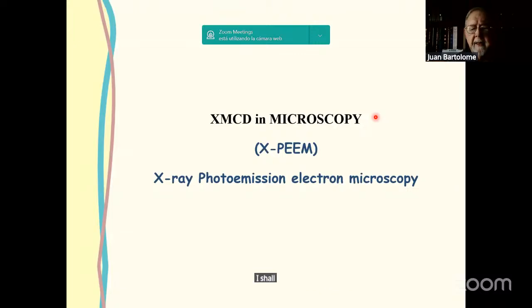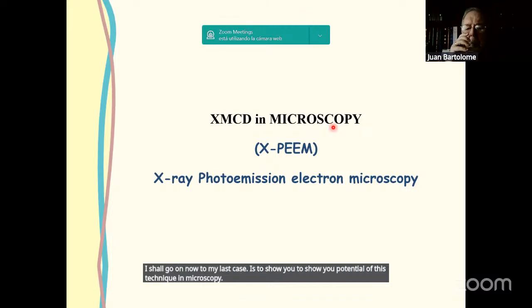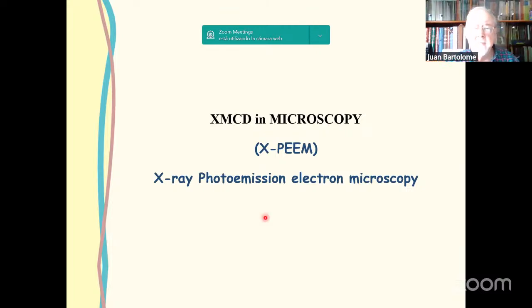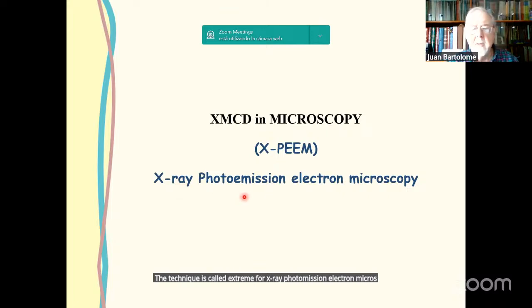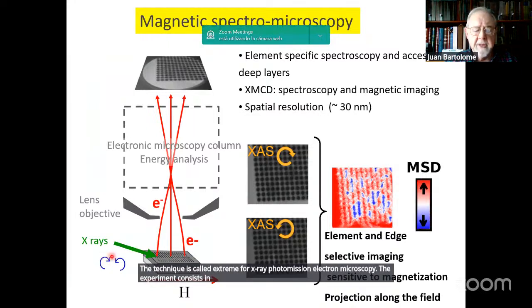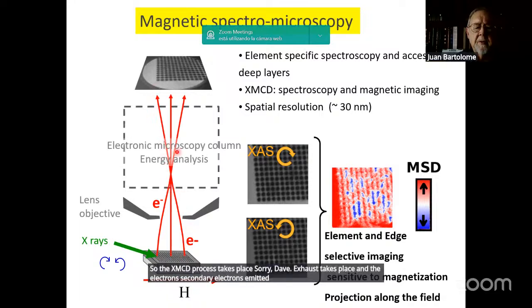I shall go on now to my last case, to show you the potential of this technique in microscopy. The technique is called X-PEEM, for X-ray photoemission electron microscopy. The experiment consists of shining X-rays, polarized either to the right or to the left, on a sample where there's an applied field parallel to it. So the XMCD process takes place, and the secondary electrons emitted are put into an electron microscopy column, which then allows us to image the surface which has been bombarded by X-rays. We can do that for the two polarizations and then calculate the differences.